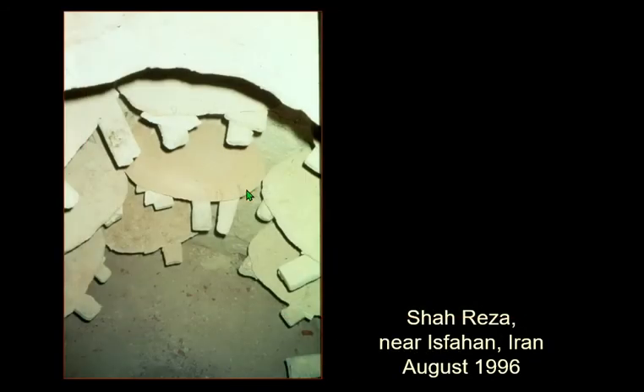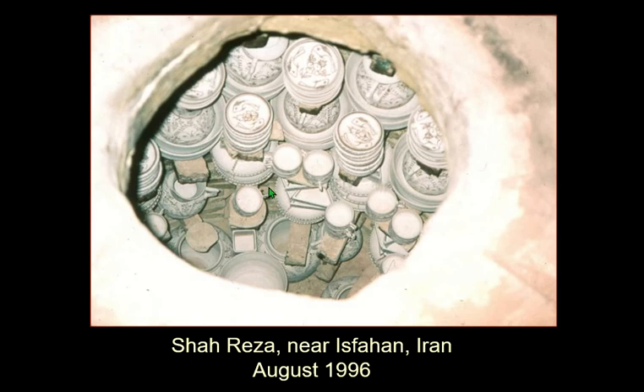And you can see it's being prepared to take pottery. These things sticking from the side are called kiln furniture. Kiln furniture is very useful because it's typically made of the same material as the pottery is made, but you don't trade it over a long distance. So if you find fragments of kiln furniture, you have found evidence of production. And this is very important for glazed pottery in particular, which is what this is. And so you can see on top of all this kiln furniture, they've mounted up all of this pottery, which has been painted and it's been glazed. So the glaze is a glass crushed to a fine suspendable material, which has then been painted or washed over the outside. And we'll be talking more about glazes in a later lecture.